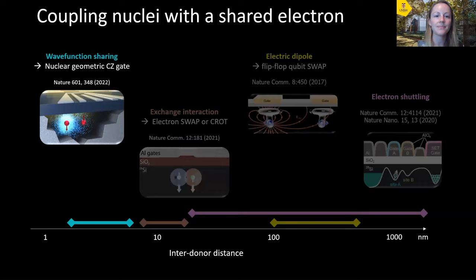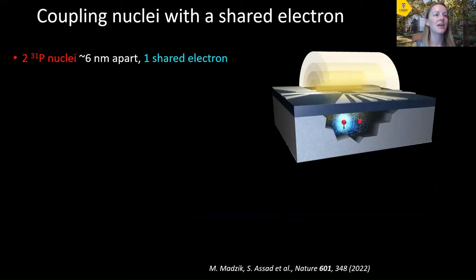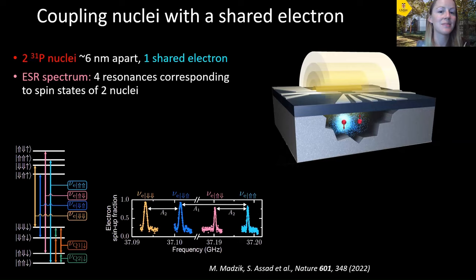So firstly, I'll start with the wave function sharing, which is where you have two nuclear spins with a shared electron. So in this device, we had two implanted phosphorus nuclei that were spaced apart by 6 nanometers. So that's pretty small. And it's so close together that these donors share the same electron. So the electron wave function overlaps both of the nuclei. And the electron spin resonance spectrum of this single electron therefore will contain 4 different resonance frequencies, depending on the 4 different spin combinations of these two nuclei. So you've got nuclei down, down, nuclei down, up, nuclei up, down, and nuclei up, up. And these each have their own electron spin resonance frequency.